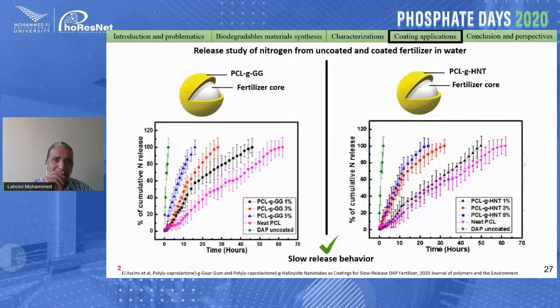We studied the release of nitrogen from uncoated and coated fertilizer in water, and as you can see, this green one is the uncoated fertilizer. We lost almost all the fertilizer after 1.5 hours. But as you can see, with 1% filler we have really good slow release of nutrient. We need almost 50 hours to release the total nutrient instead of only 1.5 hours for the uncoated fertilizer.